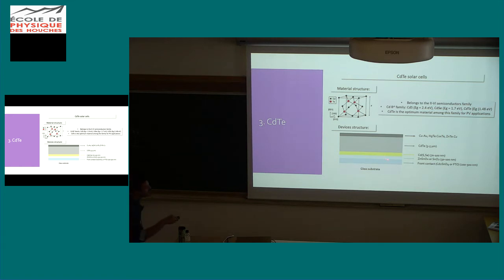And then it also has some impact on the band alignment. It's much better if it's a smoother band alignment in this structure, then you normally have less recombination than if you contact this directly with this. So it's basically protecting and improving the band alignment in your structure.